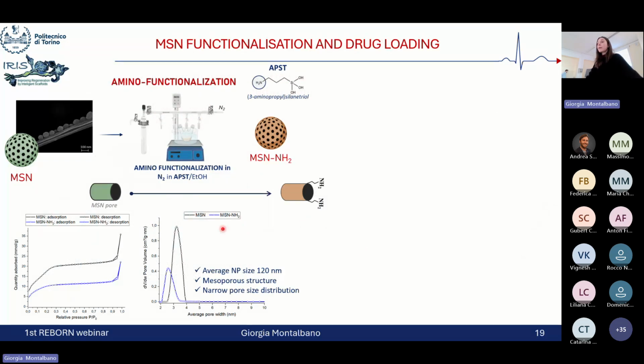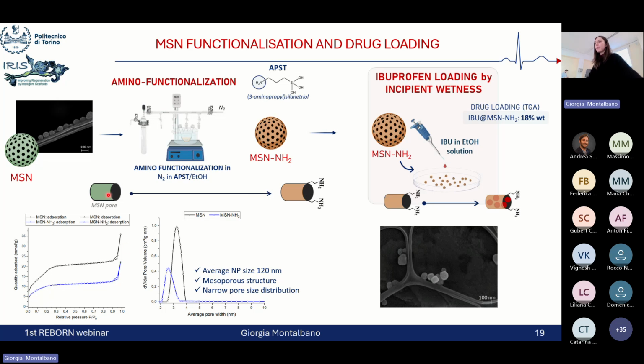So after producing our mesoporous silica nanoparticles by the sol-gel technique, we proceeded with the functionalization of the surface with amino groups, exploiting a reaction with APTS in controlled conditions in order to expose the amino groups on the surface and induce a better deposition of our alginate coating. As you can see here from the morphological and physicochemical characterization, we were successful in the design of nanoparticles with a size of around 120 nanometers, characterized by a very mesoporous structure with a narrow pore size distribution. We then loaded our anti-inflammatory drug, ibuprofen, by exploiting incipient wetness, just incubating our particles in a solution of ibuprofen in ethanol.